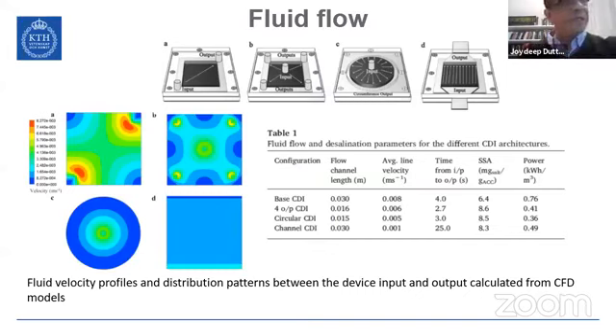If we have an electrode, this is the electrode that we use. It's a carbon cloth, which we buy off the shelf. And then if you fix it onto a flat sheet, we try to see what is the best way that we can have the maximum flow through our electrodes. While optimizing it, we have been able to see that a circular system is probably not the best, but we can have an entry point at the middle and then it flows through. It's very nice for lab use, but it's not practical because it has to be scaled up to be able to reach the people.